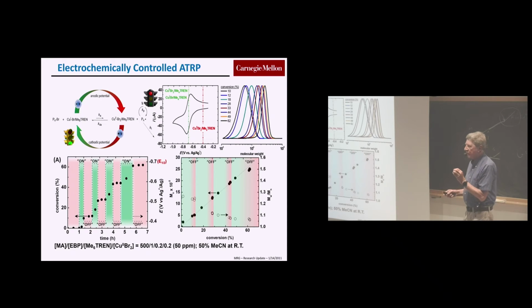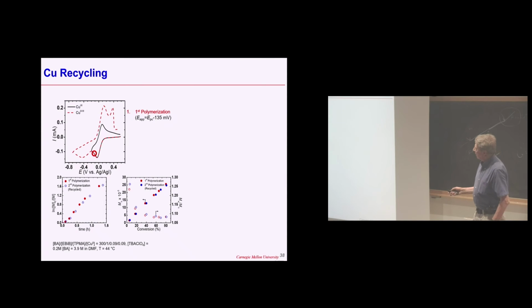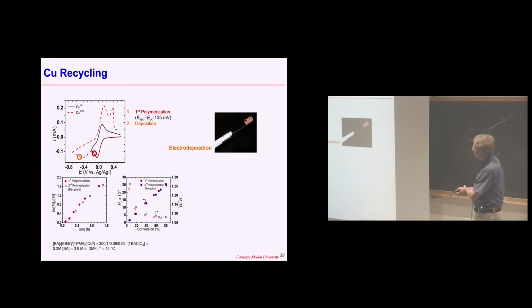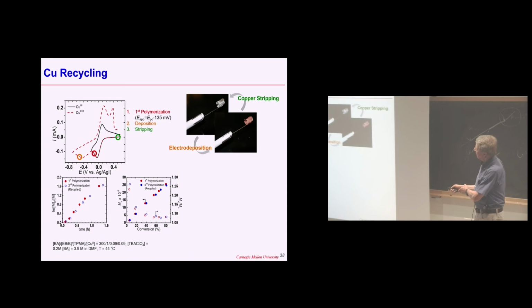So now there is a kind of question. Can I go to more and more negative potential and potentially get a faster reaction? And there is a problem. If I go to more and more negative potential, you could see that the reaction here essentially would stop. And on a platinum electrode, I have deposition of copper, and there is no more copper catalyst in the reaction mixture. The reaction stops. So this is bad news. But also it's good news because I can remove copper this way. And now if I go back to the very positive potential, I can strip this copper and put it back into solution, and then I can recycle that.